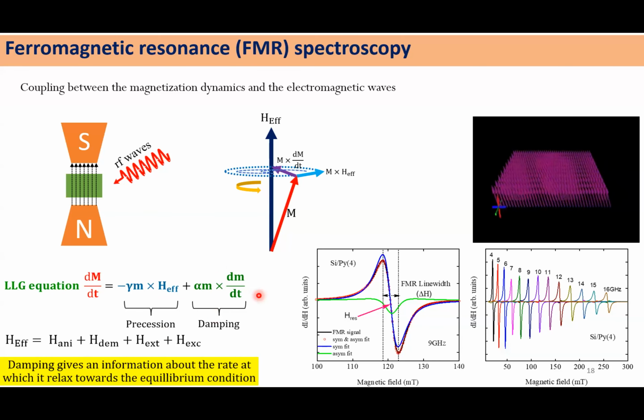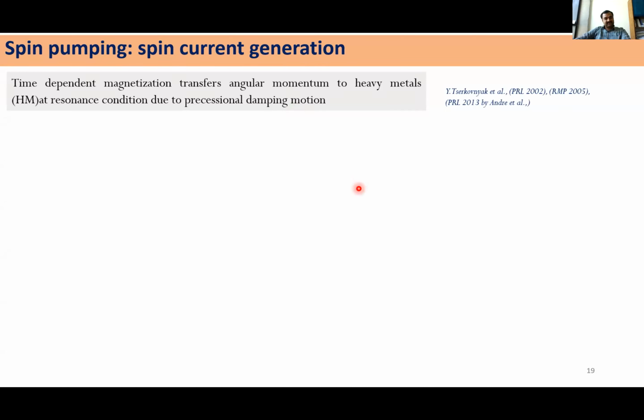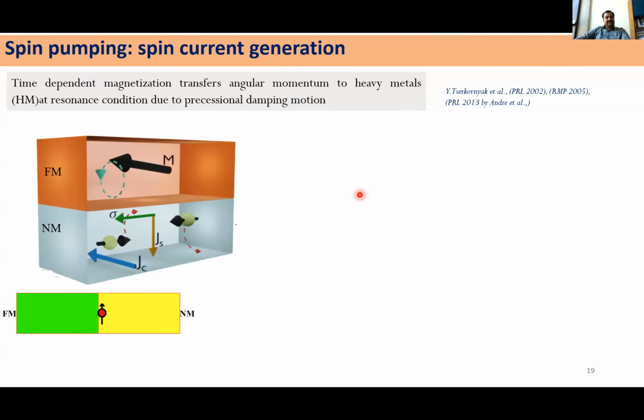Okay. So basically, we have used the spin pumping technique for spin current generation. We have used a ferromagnetic layer, that is permalloy, and then we have kept tantalum. By magnetization precession, the spin current can go across the interface, and the transfer of the spin current can be seen as a change in additional damping.